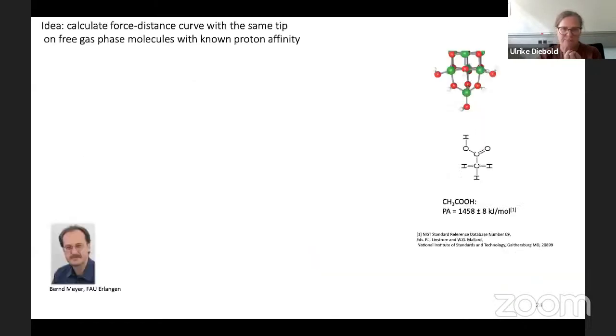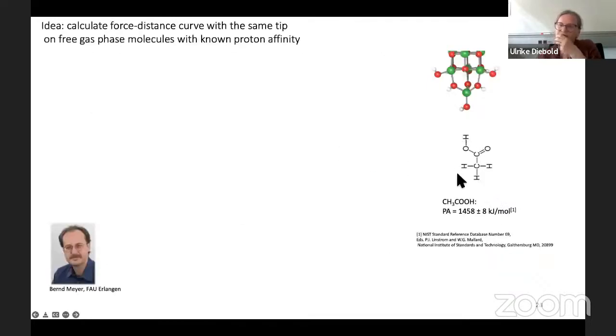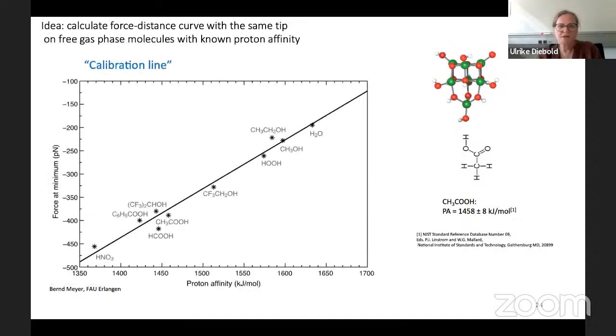But how do we get any sort of number? And this is now where we've been really brave. So we have here Bernd Meyer. He's a theoretical collaborator from FAU Erlangen. What he did was, he did these calculations for free molecules. So this would be, for example, this acetic acid I've alluded to before, with this proton affinity according to the NIST database, and he does these force distance curves for one free molecule and calculates a characteristic minimum for this type of tip. And he does this for a large variety of gas phase molecules, all tabulated. And this is the force minimum calculated. And you can see this is a nice straight line that we call our calibration line.